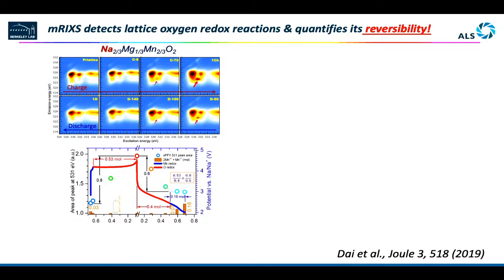So we went through several materials, and this is one material. It's a sodium battery material. It's a material that does not show the oxygen release. I just showed you most of the materials, so this is like lithium cobalt oxide. They are fairly stable if you charge it to relatively high voltages. So meaning if the oxygen is getting oxidized in this material, it should be contained in the material. And then we do see this kind of feature with a red arrow pointing to where you charge and then discharge. So you see the feature going up and down.